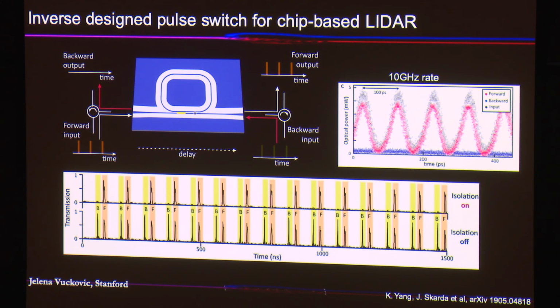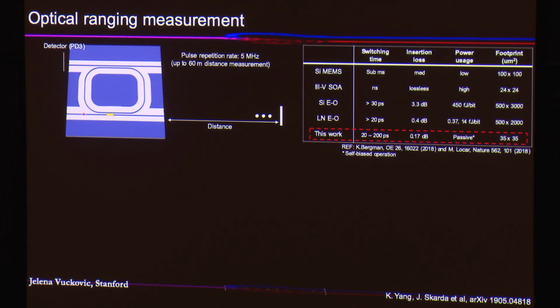And we can actually operate also at the 10 gigahertz range, as shown here, where you see that you're blocking backward signal, even if you're driving the system at the 10 gigahertz rate. So why is this interesting? Well, it's a pretty complicated function that you can just implement with a tiny block of silicon. This doesn't require anything other than writing these two rings and a little bit of the waveguide in between and optimizing how coupling looks like for the system.